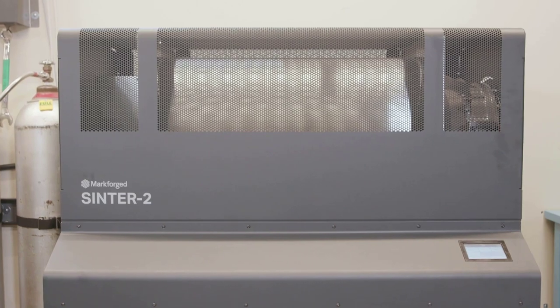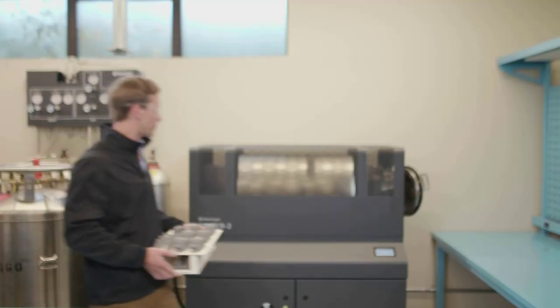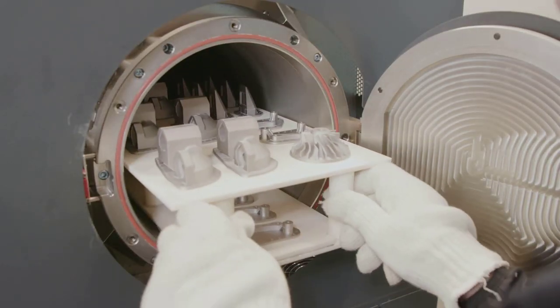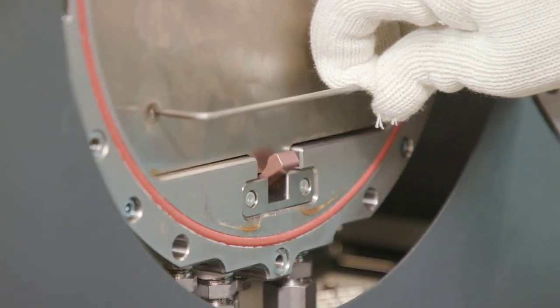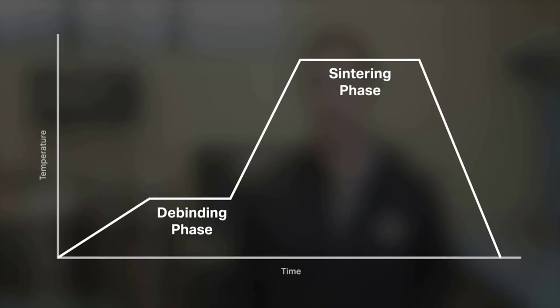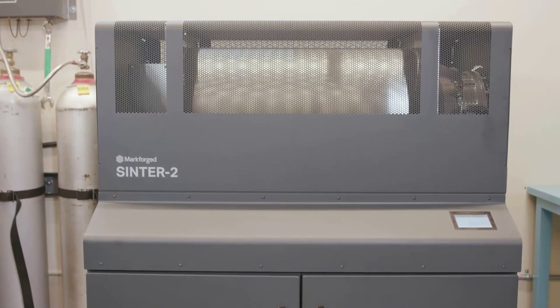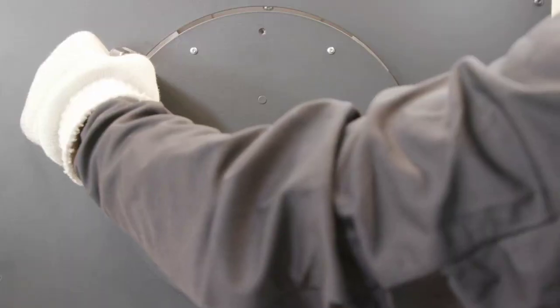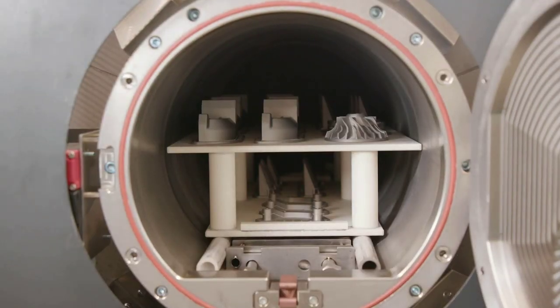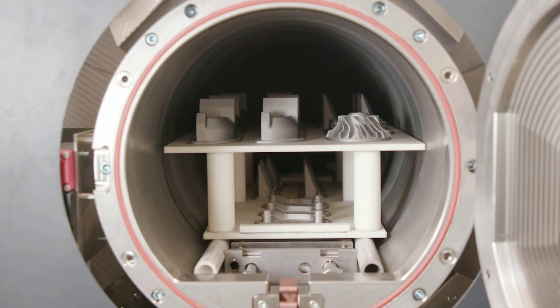This is Sinter 2, a furnace designed for mid-volume production runs and larger printed parts. Sintering transforms a print from a lightly bound collection of metal powder to a fully finished metal part. First, the temperature ramps slowly to burn away the trace amounts of remaining binding material. Then, temperature ramps closer to the melting point of the material, allowing metal particles to start to fuse together to create a strong metal part. Markforged sintering furnaces use a carbon-free retort to ensure part quality and alloy composition standards are met for our finished pieces. Each run takes about a day and can be monitored remotely using the Eiger software.